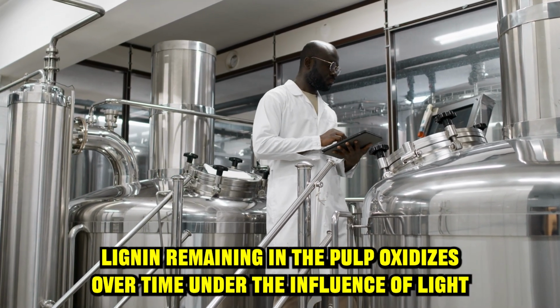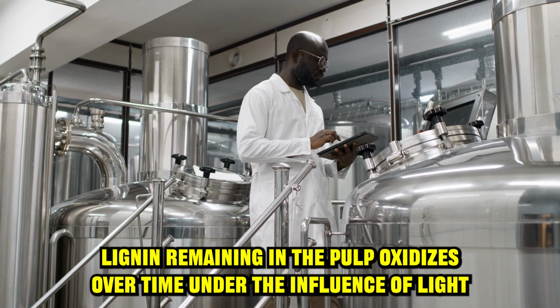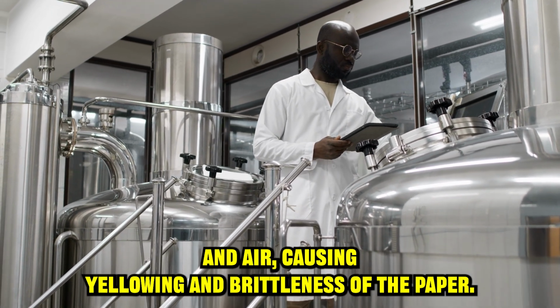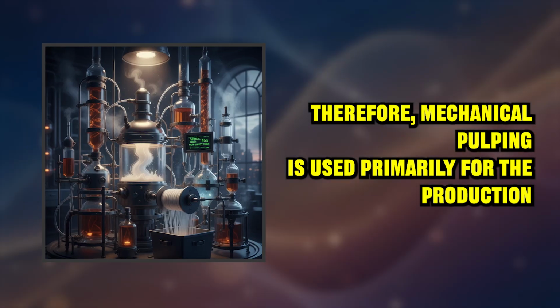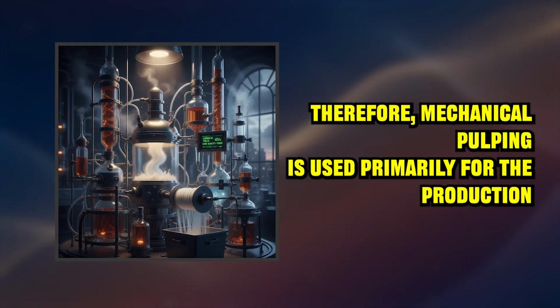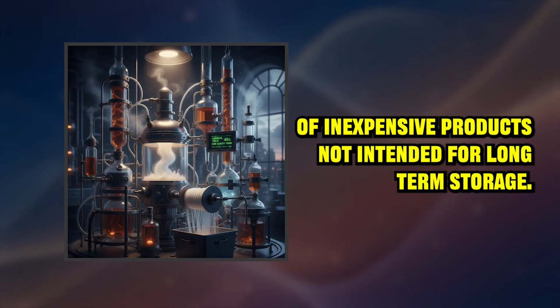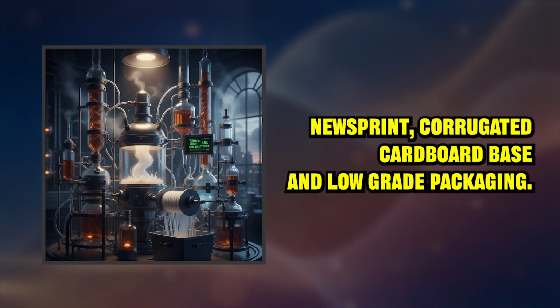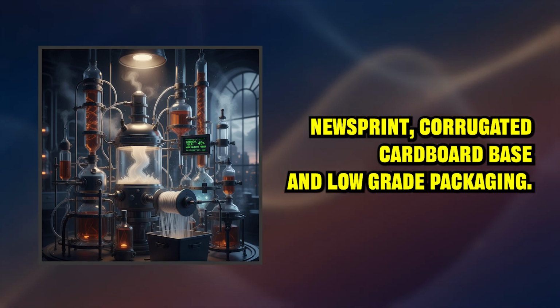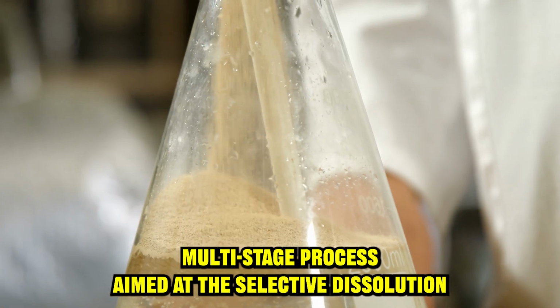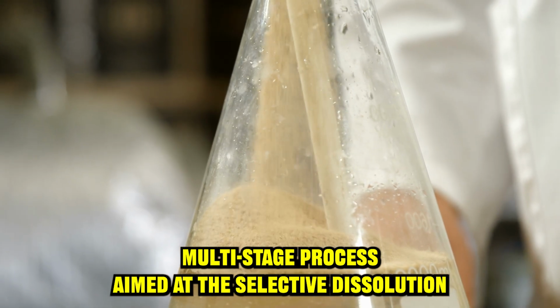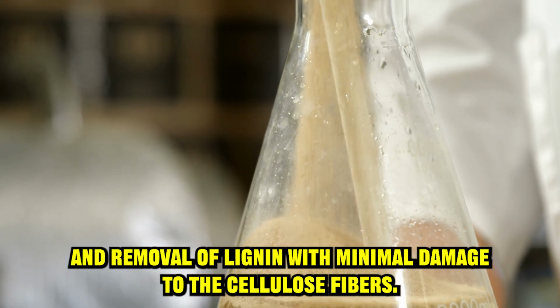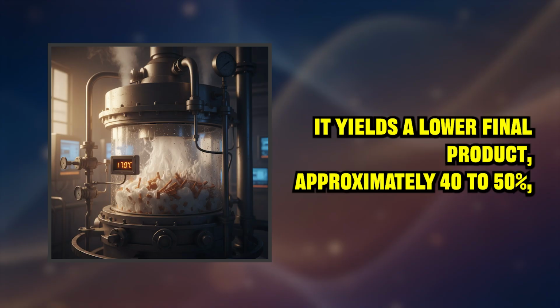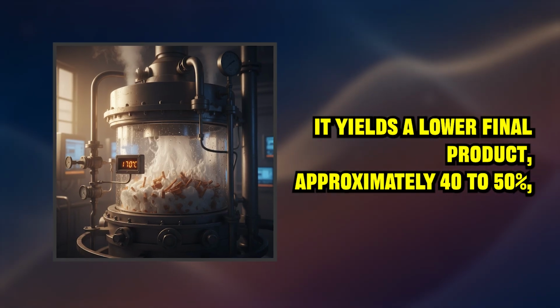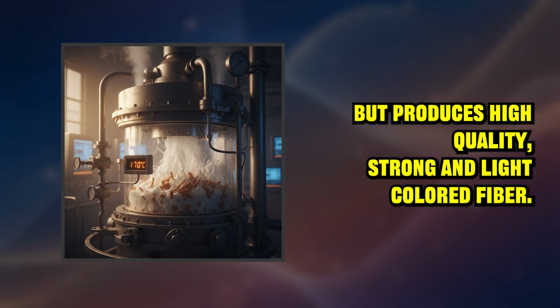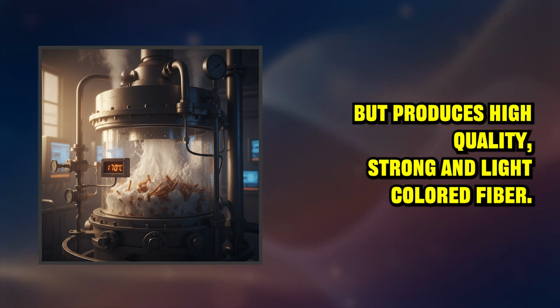Lignin remaining in the pulp oxidizes over time under the influence of light and air, causing yellowing and brittleness of the paper. Therefore, mechanical pulping is used primarily for the production of inexpensive products not intended for long-term storage, newsprint, corrugated cardboard base, and low-grade packaging. The chemical method is a complex multi-stage process aimed at the selective dissolution and removal of lignin with minimal damage to the cellulose fibers. It yields a lower final product, approximately 40–50%, but produces high-quality, strong, and light-colored fiber.